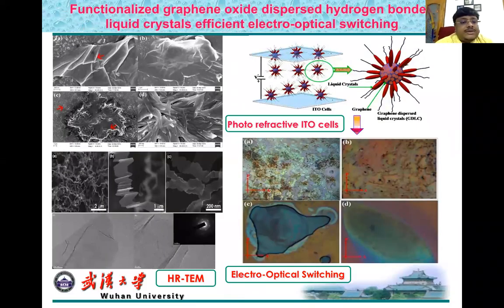And this is graphene oxide. First is graphene, and when graphene comes in contact with liquid crystals, a nanofiber-like structure evolves. And here is a nano ribbon. We fabricated high quality nano ribbons, and those